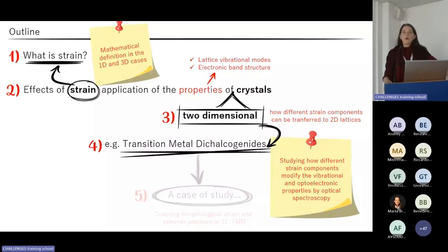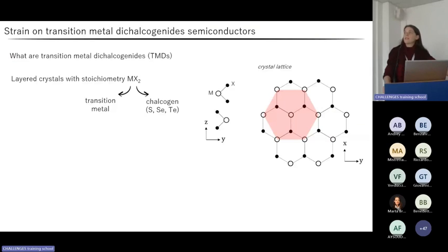For the sake of simplicity, all the examples I have selected involve crystals belonging to the well-known family of transition metal dichalcogenides, or TMDs. These are crystals with stoichiometry MX2, in which M is a transition metal and X is a chalcogen among sulfur, selenium, or tellurium. They are characterized by a layered structure with a single layer consisting of a plane of metal atoms sandwiched between two planes of chalcogens.